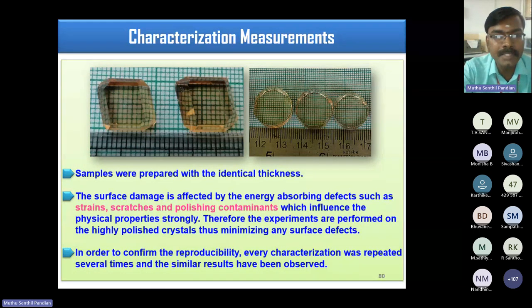Samples, meaning crystals grown by the SCST and SR methods, were prepared with identical thickness. The surface damage is affected by energy absorbing defects such as strains, scratches, and polishing contaminants, which strongly influence the physical properties. Therefore, all the characterizations were performed on very highly polished crystals so that one can minimize any kind of surface defects in the conventional and SR method grown crystals. In order to confirm reproducibility, all the characterizations were repeated several times, and more or less similar results were observed for the SCST and SR method grown crystals.